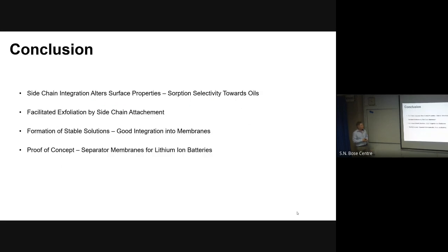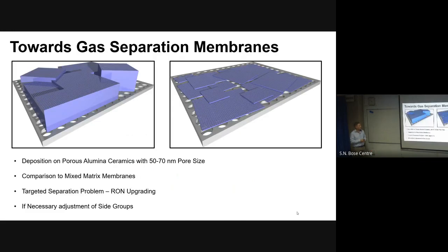So to conclude my results, the side chains alter the surface properties, so we get a nice sorption selectivity towards oils and other hydrophobic molecules. We can exfoliate the materials much more easily, so the side chains help in the exfoliation process, as we saw from the AFMs. We form quite stable solutions, so we can integrate them easily into membranes. And as a proof of concept, we use them as a separator membrane for lithium-ion batteries. That works. So, what are our next steps in this research?